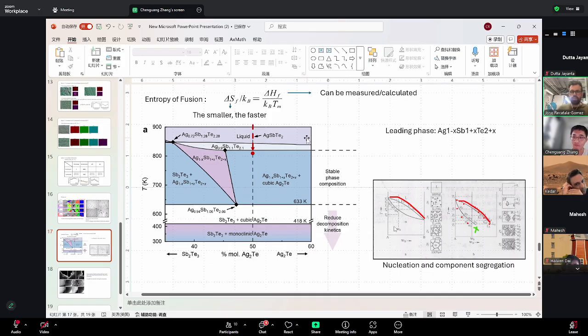So this one over here is heating. You start with the precursors and you start heating and you collect spectra, and you do that for different composition ratios. So you have different points in X that map to different points in T, and you get the phase fractions from in situ.